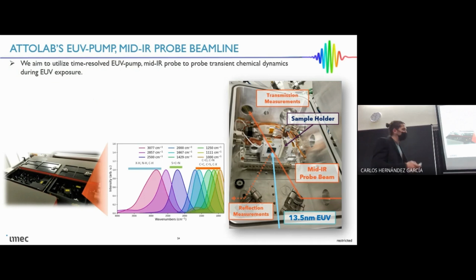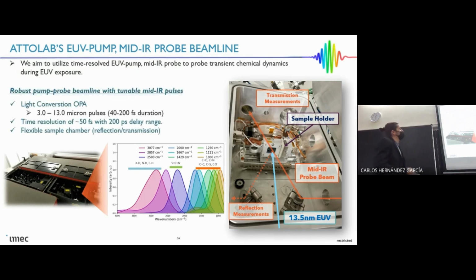effect in these resists. And so what this gives us is a nice beam line with tunable mid-IR pulses with a decent time resolution, which varies depending on the pulse that we're producing, along with a stable delay line and a flexible chamber for performing these experiments.